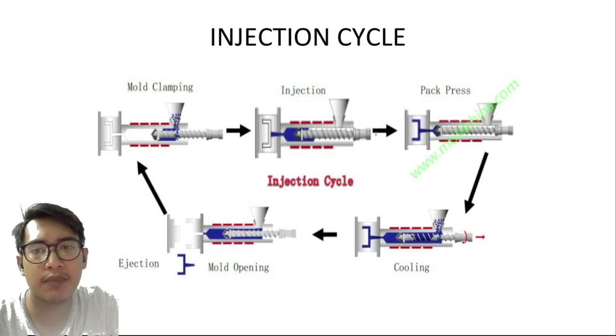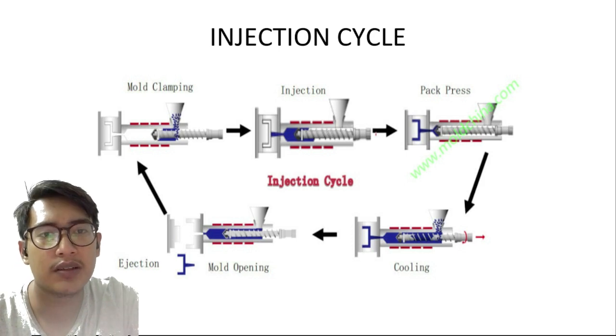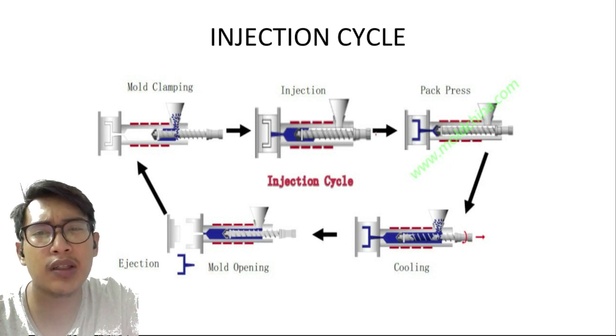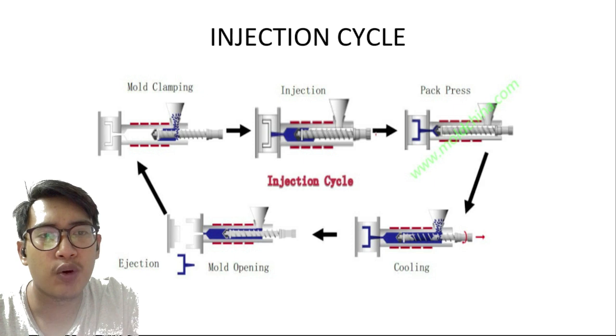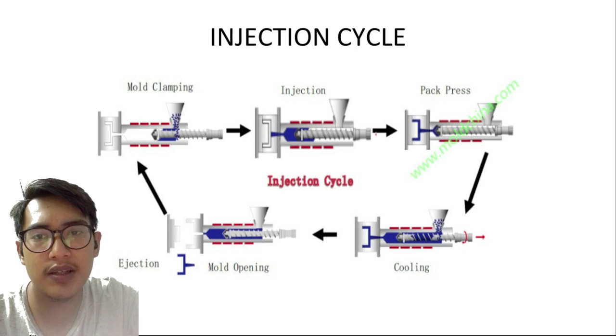The screw advances and plastic flows into the mold. Temperature, pressure and shear rate. Injection speed, the rate at which the ram screw moves, is the most critical variable during fill. A polymer flows more easily as injection speed is increased. However, injection speed that is too high can create excessive shear and result in problems such as splay and gate blush. More importantly, heat from a higher shear rate can degrade the plastic, which adversely affects the properties of the molded part.